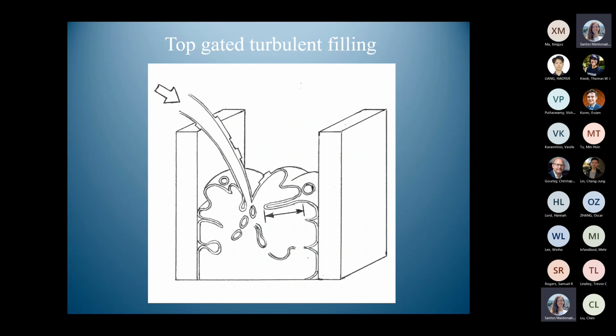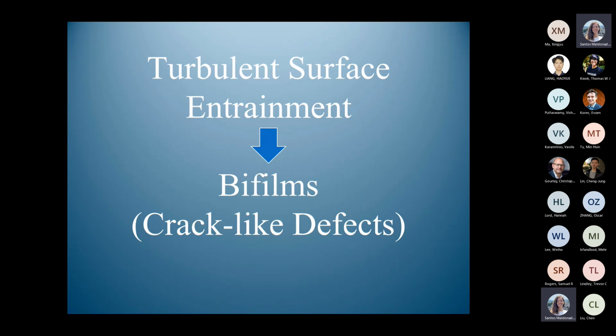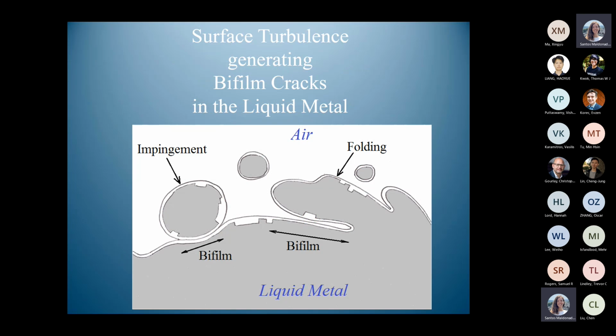Anyway, so this is the reality of our pouring systems. And so the turbulent surface entrainment leads to bifilms, which are kind of crack-like defects in the liquid. And here's another instance where a folding action produces the bifilm, but also an impingement action, again, leads to a biofilm. All these things lead to bifilms coming together, dry side to dry side. It's fundamental to the way entrainment occurs. When the surface goes in, it always goes in dry side to dry side.